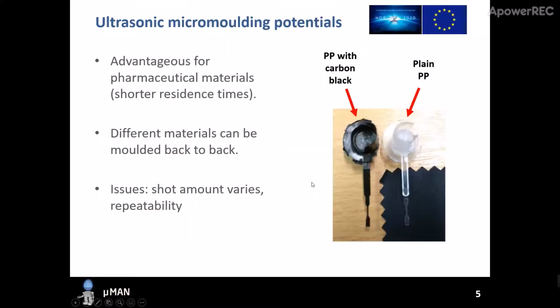There are some advantages and potentials for this technology. It is good for pharmaceutical materials because we have very short residence times, or no residence times at all, because the process usually takes place within 3 to 5 seconds. So the polymer is exposed to elevated temperatures for quite short times as compared to conventional injection molding or micromoulding, where we have a screw and a barrel system, and the polymer melt is exposed to elevated temperatures for hours in some cases. So this is an advantage for pharmaceutical materials, which are quite expensive at times.